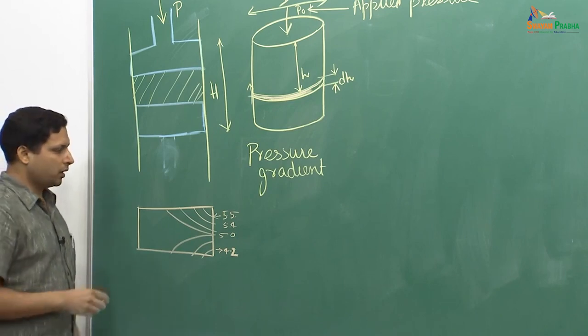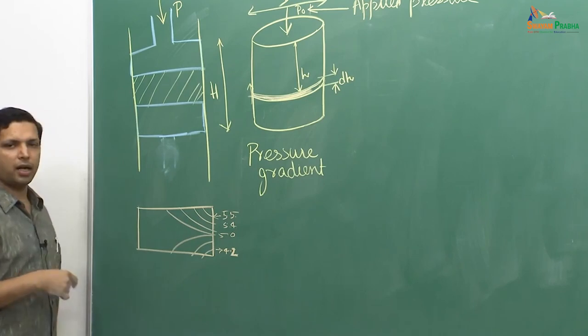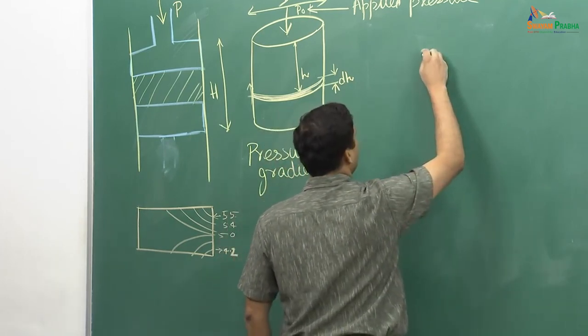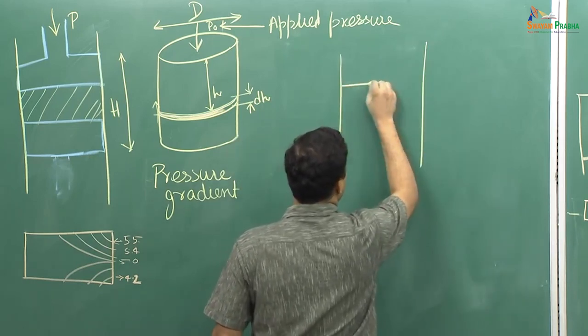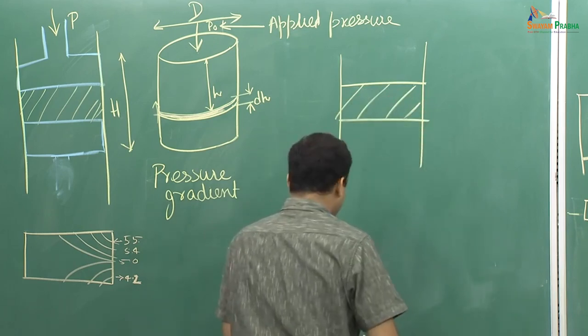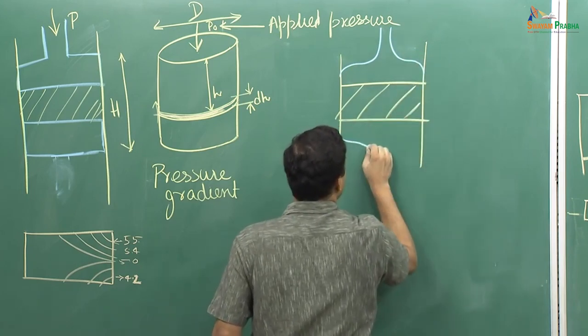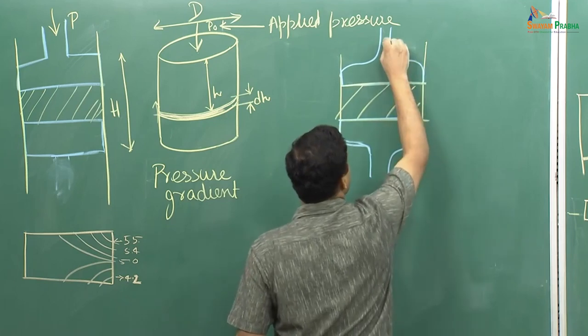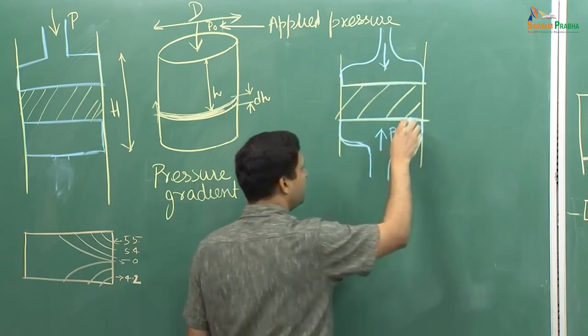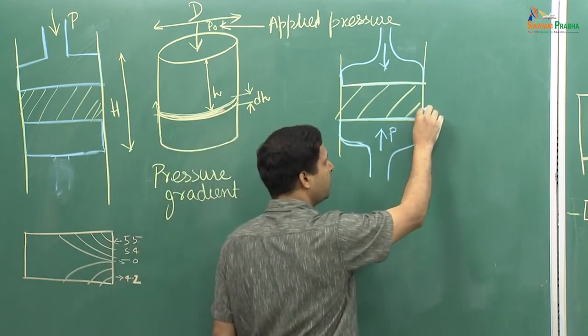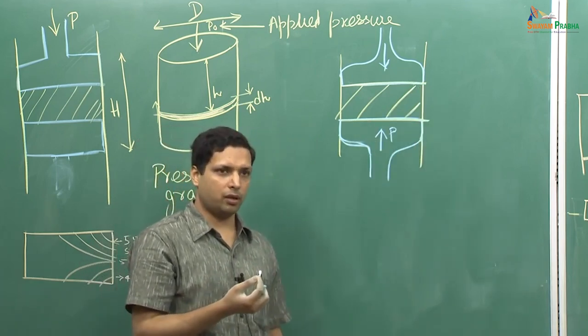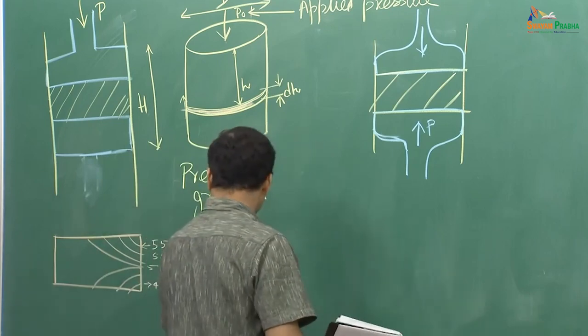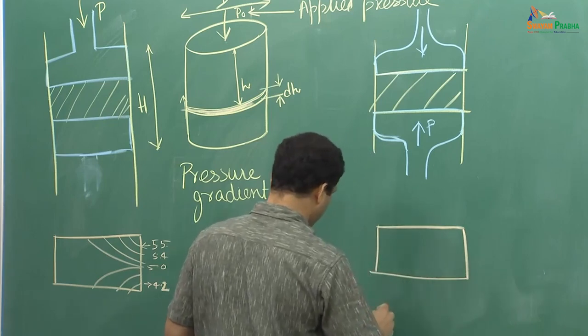However, if you want to get the same dimension with less pressure distribution and less density variation, one way is to use a double-ended piston. You will have this piston moving in from one side and this piston moving in from the other side. Therefore, the relative motion of the particles becomes smaller, the overall average movement of the particle is smaller, and hence the friction faced by them would be smaller.